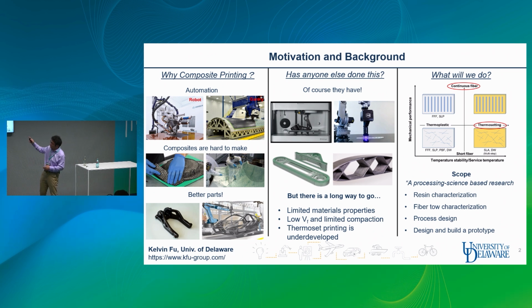But if we look at those companies who say they are making composites, in my opinion, I don't believe they are making composites, because when we evaluate composites, there are a few factors we need to consider. The first one is fiber volume fraction. Normally only 50% or 60% fiber by volume in the matrix can be considered a composite, especially for aerospace grade composite materials. If we want to achieve very high mechanical strength, we need to put a lot of continuous fiber in the material.